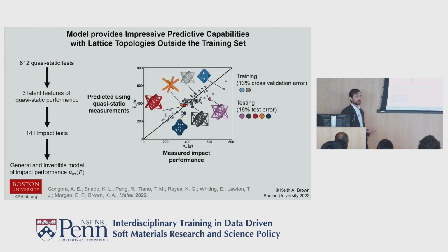And this is the result of that kind of approach. Here we have the predicted performance using quasi-static measurements versus the measured impact. The training data is the blue and the gray data, and we have good cross-validation error here, about 13%, which is commensurate with the variation we see in experiment.